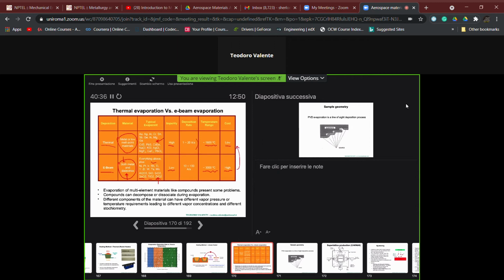But have a look, in any case, to these figures. You see here, with a basic configuration, that's the deposition rate. In the best cases, we can achieve something in the range of 20 angstrom per second or 100 angstrom per second, so very, very low deposition rates. So if you want to avoid any deleterious effect related, for example, to residual stress, and you want to fabricate a 1 millimeter thick coating by using this technology, you could need even 1 year of treatment. That is a solution which is not industrially useful. And so thin films, thin coatings, due to the fact that the deposition rate is very low. And these are very low values.